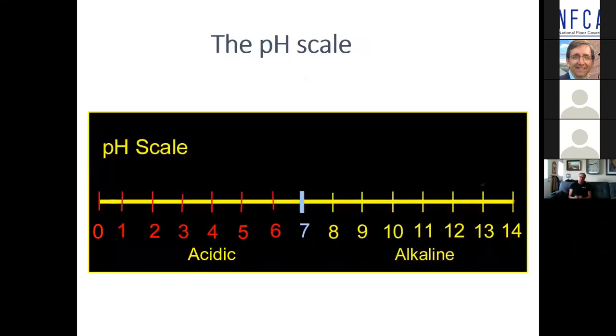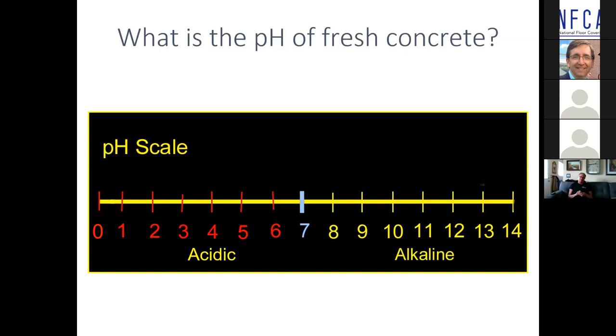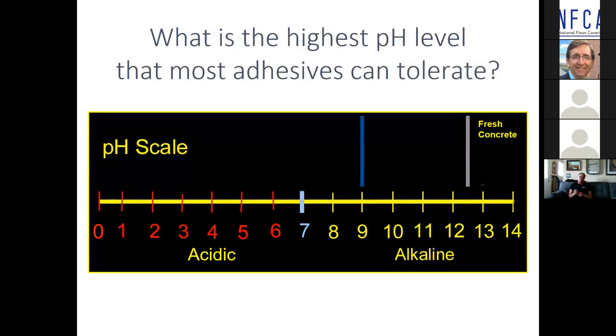Okay, we talked about it being a 0 to 14 scale. Distilled water, deionized water, pH is 7, but it's a logarithmic scale. When you go from 7 to 10, you're talking a concentration difference of 1,000 times. Concrete, when it comes down the chute, fresh concrete, is always going to test 10, 12, 12 and a half, 13. What's the highest pH level with most manufacturers? 9 to 10. So what's wrong with that picture? How can we have flooring adhesives that can only tolerate pH levels of 9, 10 going down over concrete, which, without apology, would measure fresh concrete at 12 and a half and 13?